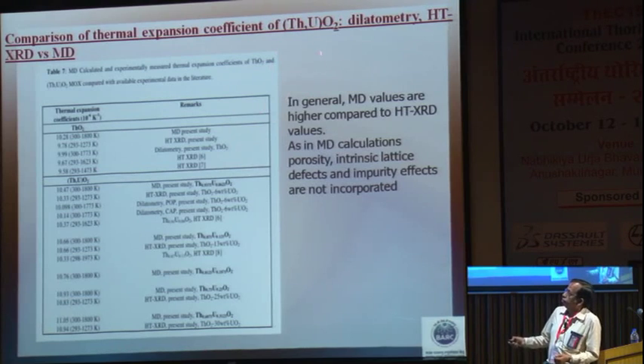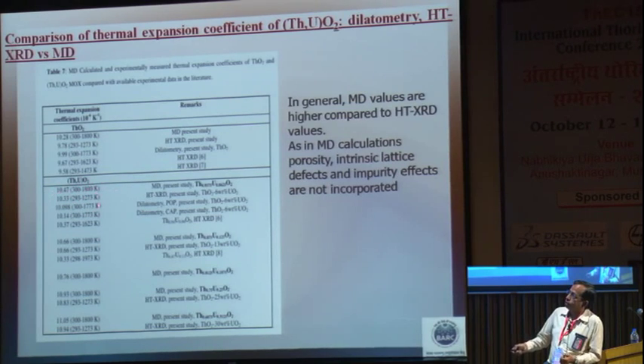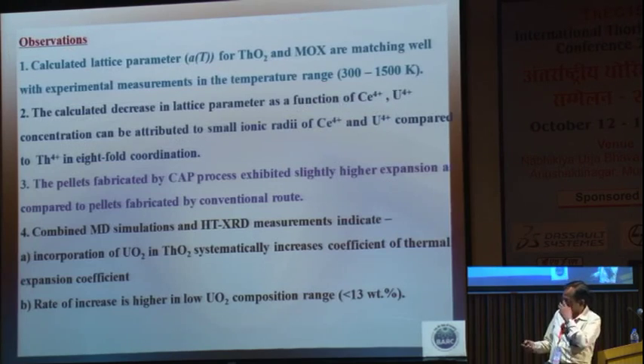This comparison is for thorium uranium oxide determined by dilatometry and high temperature XRD versus molecular dynamics. You can see the molecular dynamics results are listed here for pure thorium and thorium uranium oxide, and you can again see that the agreement between molecular dynamics and experimentation is very, very good. So, this would indicate that the approach used is correct. The observations have been summarized here, and I will just run through this.